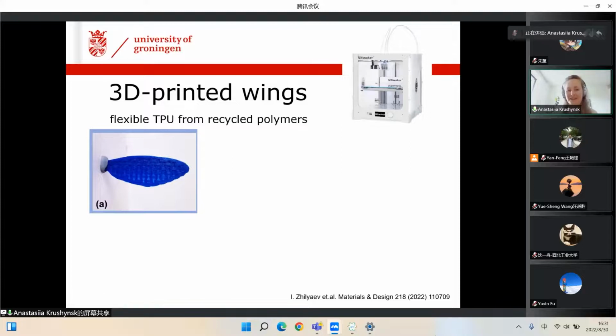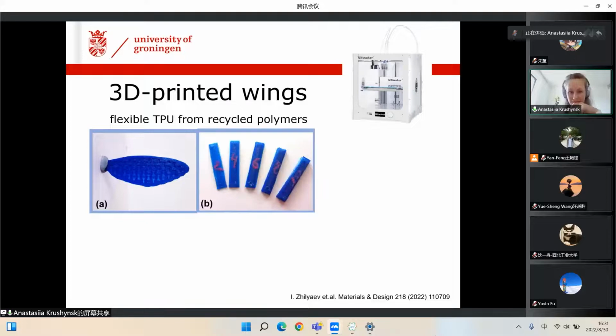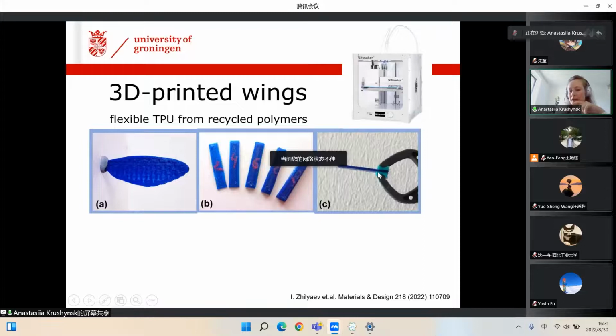To give you an idea how this flexibility works, and because we are not in a real audience but online, I give you here some demonstration. So we printed several samples which have different out-of-plane thickness. So for the first sample, we have 2 printed layers, for the next 4 printed layers, and so on, and for the last 10 layers. And this number of layers is used in the design of the wing. And then we fix one end of this sample, and the other will be loaded with a static mass. So this is not to test anything, but just to show you how flexible or rigid the material can be.